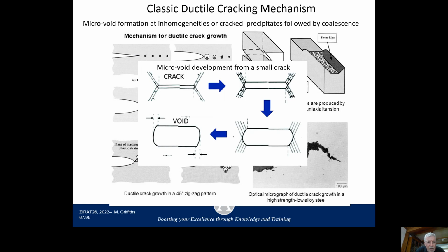Having cavities, swelling, and a propensity for easier cracking is not hard to imagine, because the normal form of ductile fracture involves the creation of micropores just by nature of the cracking process, and basically pore cavity coalescence.